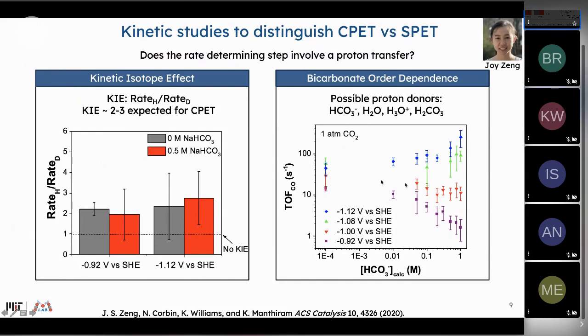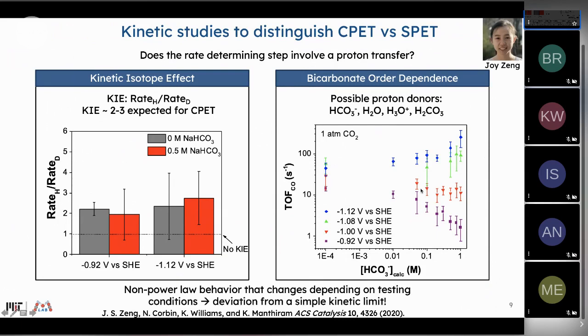And as I increase the potential at the electrode, going to higher overpotentials, eventually bicarbonate has no impact on turnover frequency, and at much higher overpotentials, it is in fact promoting of CO2 reduction. So this is something that one can't easily linearize; there is non-power law behavior and a deviation from a simple kinetic limit.